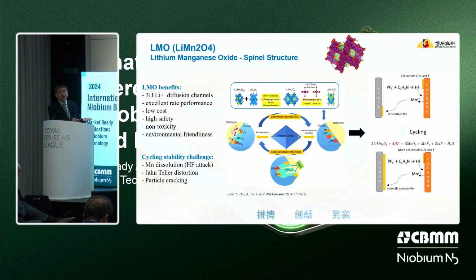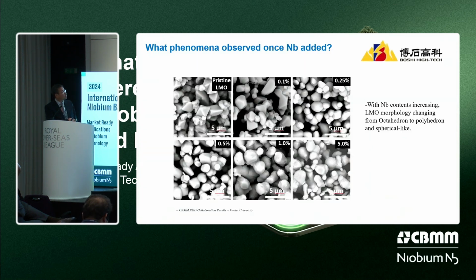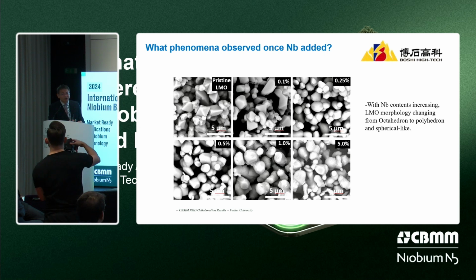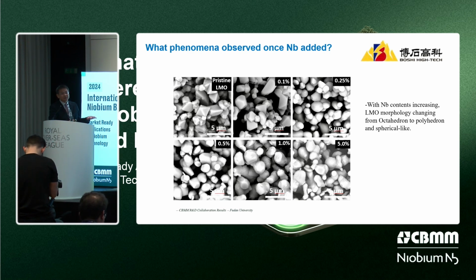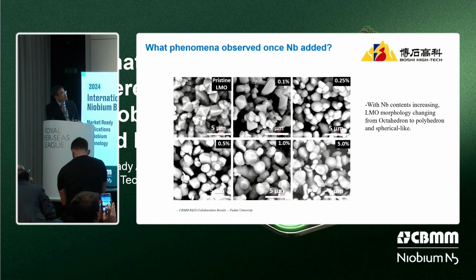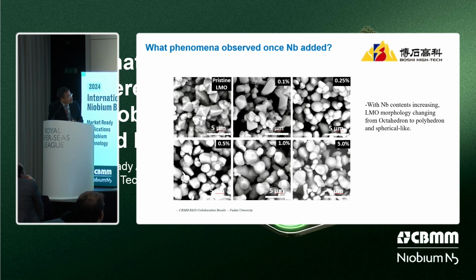Let's see what role niobium could play to improve performance on these points. We are interested in what phenomena we could observe once we added niobium into LMO. This we think is the most important phenomenon we observed. Once we added niobium into the LMO, whether it's doping or coating depends on the temperature, time, and also content. If we add niobium from this content to this content, the main phenomenon we could observe is the morphology change from octahedral to polyhedral, and also spherical-like. I think this is a very important phenomenon for LMO.